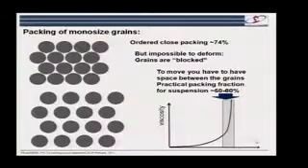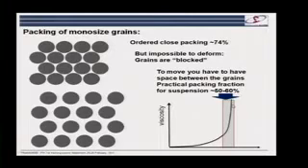It would also apply to any material that needs to flow. You see that as the amount of solid volume increases along here, the viscosity, that's the difficulty of moving the material, increases until you reach a kind of limit here. If you try to go beyond this limit, nothing moves, it's all blocked.